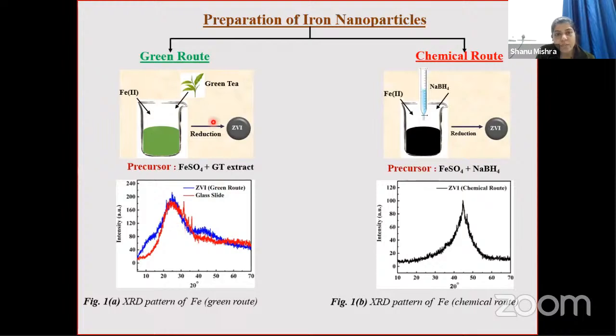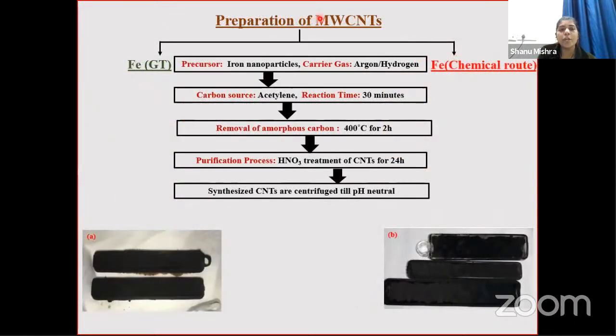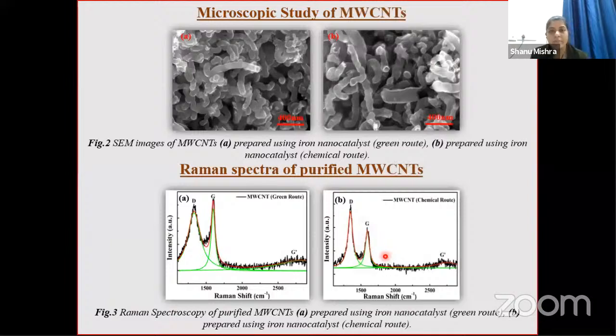Synthesis of CNT using green tea synthesized iron nanoparticles was not yet discovered. So we have synthesized MWCNT via the CVD method, choosing these two catalysts as precursors, and we tried to keep the rest of the experimental parameters constant. Here we have the same carrier gas and the same carbon source, and the synthesis procedure is followed by carbonization and the purification process. These are the images of synthesized MWCNT after we remove it from the CVD. After the synthesis, we characterized our sample through scanning electron microscopy and Raman spectra.